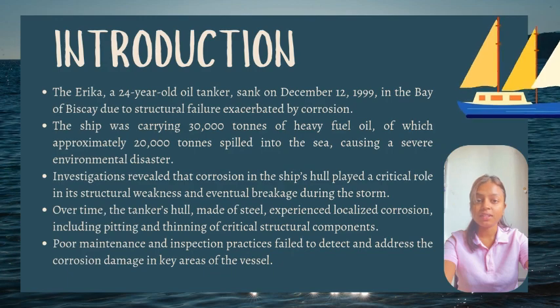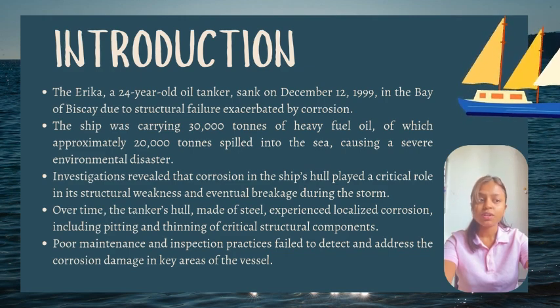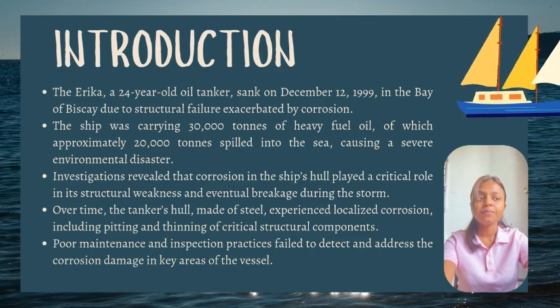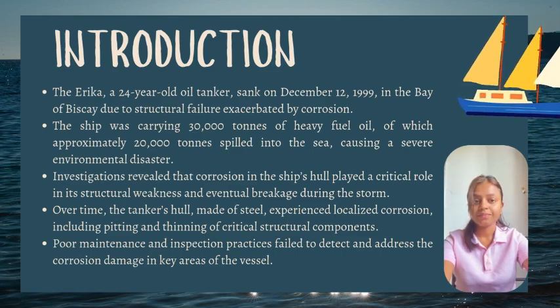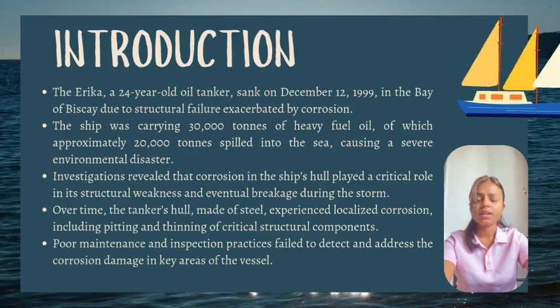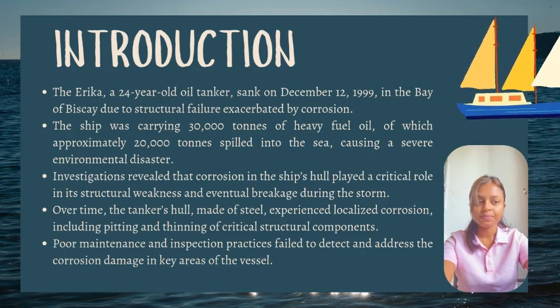Investigation revealed that the corrosion had caused pitting and thinning of critical structural components, weakening the hull over time. So poor maintenance and inadequate inspection practices contributed significantly to the vessel's failure, as key damage went undetected. The rough sea conditions and storm during the voyage further stressed the corroded hull, leading to its eventual breakage.